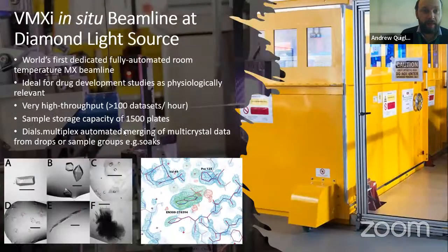Very quickly then for VMXi, as I mentioned, this is an in situ beamline. So instead of cryocooling your crystals, we're collecting data from crystallization plates. So it's basically the world's first dedicated, fully automatic room temperature MX beamline, and it should be ideal for drug development studies that are physiologically relevant. It's very high throughput, so we can collect well over 100 data sets per hour. We have capacity to store 1,500 crystallization plates on the beamline that are robotically loaded when we want to collect.